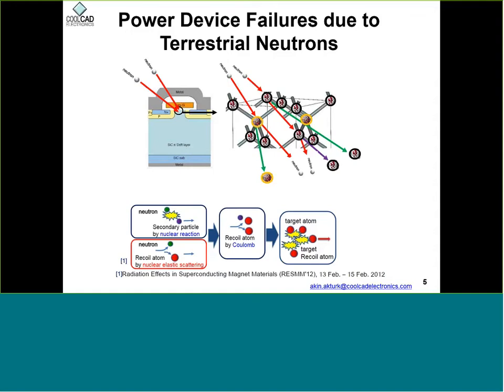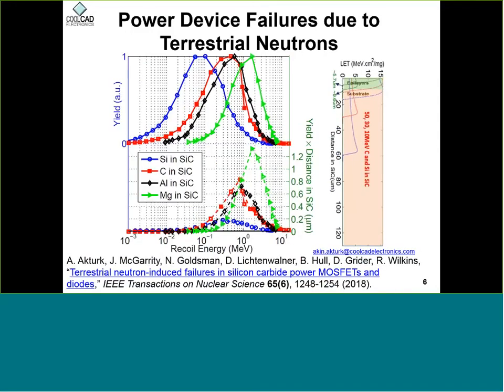In addition to the primary knock-ons, you can also have secondary knock-ons, or you can have nuclear reactions and the original atom converting into some other element. So in silicon carbide, we have silicon and carbon. And in the upper layers, we may have some oxygen and aluminum or other things. So when a neutron goes into the silicon carbide power device, it's most likely to hit a silicon or a carbon atom. And the figure on the left, the top part shows what kind of energy ranges that can create as far as primary knock-ons are concerned.